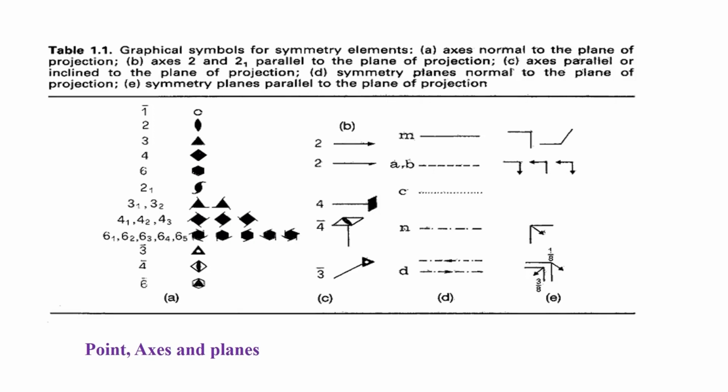That means, if I take for example a 2-fold axis, the 2-fold axis will have an x, y, z, and then if the 2-fold axis is along the y axis, we will have a minus x, y, minus z. What you notice is, if you operate the 2-fold axis once again on minus x, y, minus z, you will get back x, y, z.